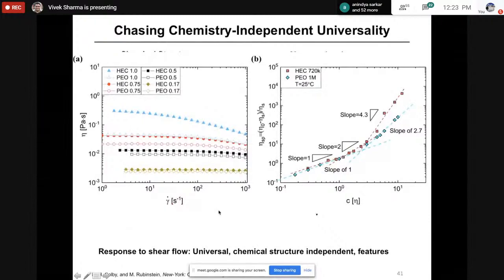So if we make shear rheology measurements, what we find is below the C star or overlap concentration, which turns out to be the same for these because coil size is the same, the behavior is indeed matched. So this gives you an example of how chemistry-independent universality exists for polymer solutions. They give you the same response as long as the coil size is similar in dilute solution. Above C star, above overlap concentration, HEC can go to entangled state more quickly, and so it has a stronger slope. But let's just focus on dilute solution.